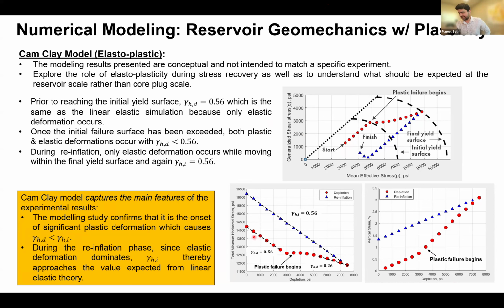And during that, before the sample reaches the yield surface, which is when the plastic deformation would start happening, this is the elastic regime. When we're in the elastic regime, you see the depletion coefficient is this number, 0.56. When we get to the yield surface, plastic failure begins, and the yield surface progressively moves with further depletion. And this is the final yield surface. And you can see this is very different from what's happening here.